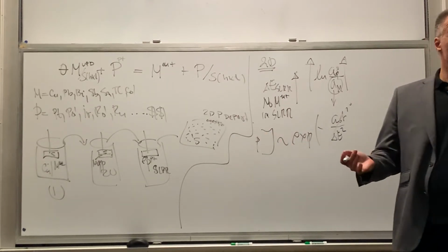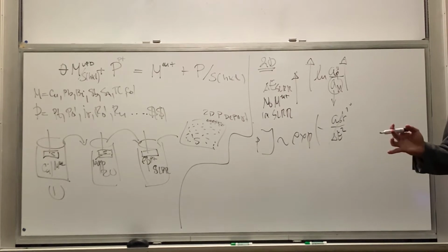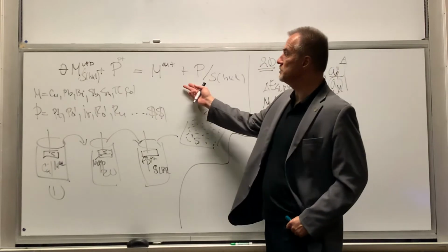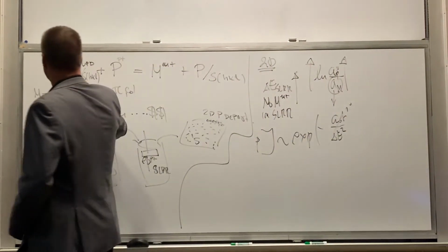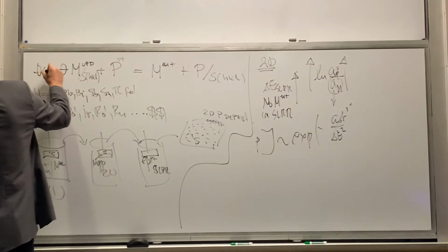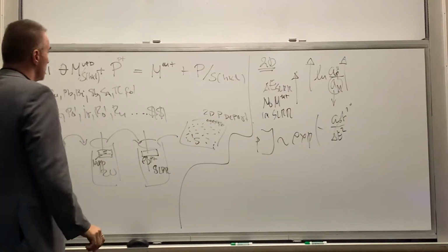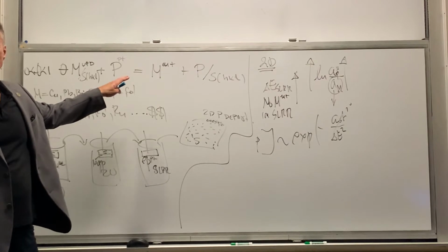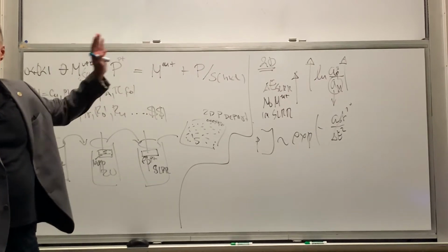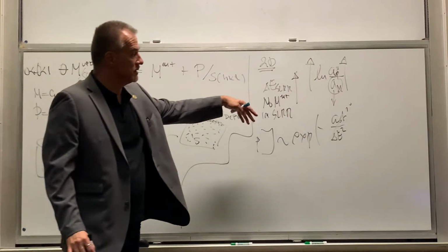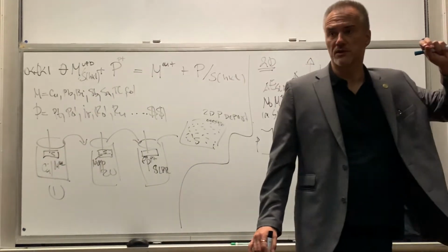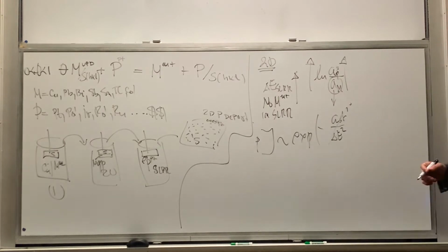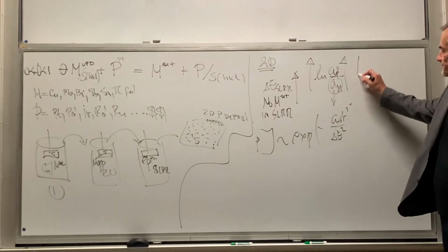And we have a huge nucleation rate, right? But we have a limited amount of deposit, according to this stoichiometry, because this theta could be between 1 and 0, right? So you can only get up to a monolayer of P. Because you have a huge driving force for nucleation, you will get a gazillion small clusters which are actually reduced to the ultimate size of two-dimensionality, right? We covered that, right?